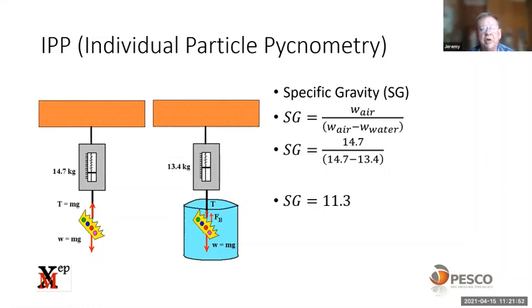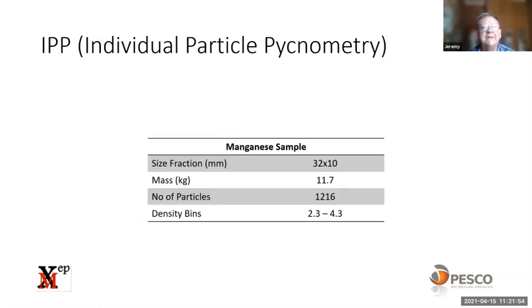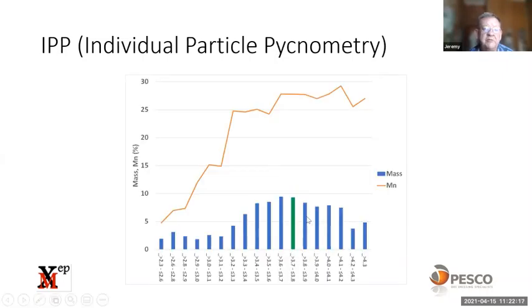So we do this on a particle by particle basis. Here's an example from manganese. So the size fraction was 32 by 10. The starting mass was 11.7 kilograms, and in that mass, there was a total of 1,216 particles. And after each particle had been weighed and its density calculated, it occupied the density range from 2.3 up to 4.3. So if we look here, we've got a graph of the results. On the x-axis, we have the different density bins.